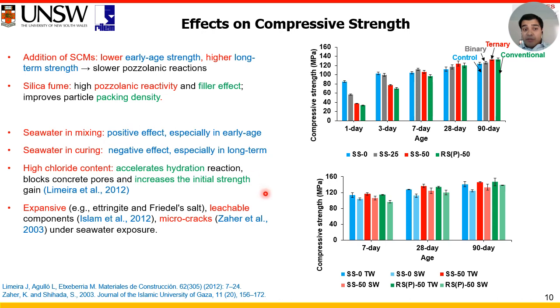When seawater was used in mixing, it had a positive effect, especially in the early age. However, when the concrete specimens were exposed to seawater for a long time, it had some negative effect. This is because the high chloride content in seawater can accelerate the hydration reaction, especially in the early age of concrete. It can block the concrete pores and increase the initial strength gain. However, when concrete is exposed to seawater for a long time, expansive and leachable components form, and also it can create micro cracks on the concrete which can deteriorate the compressive strengths over the long term.